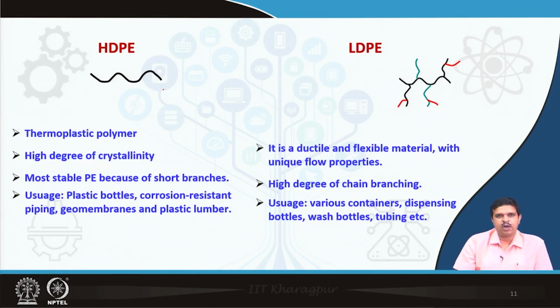So, this is basically the branching in the high density polyethylene, which is almost zero or very less. That means, obviously as discussed in the last classes, that the crystallinity, that is the more orderedness, the crystalline domains will be higher, and that is why this kind of polymer, that is the high density polyethylene, will be more stiff and will show the thermoplastic nature. The use of this kind of HDPE is that it is more stiff, more hard, and used as household materials.